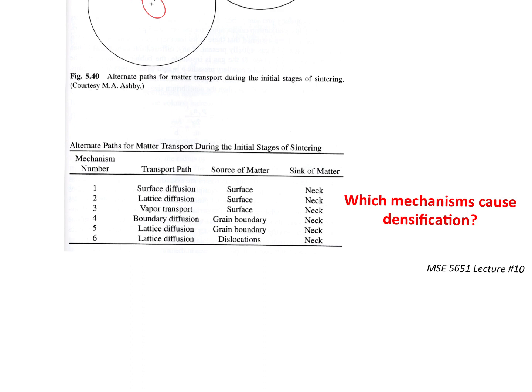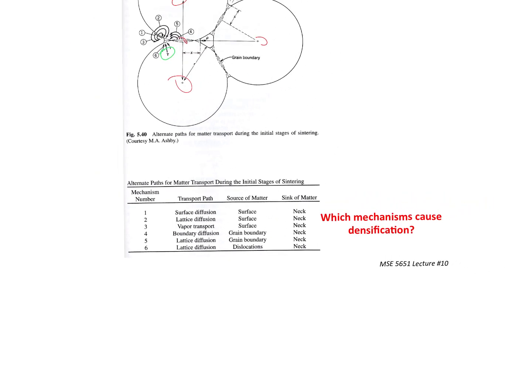You're taking it from the surface and you're transporting it to the neck, but you're not shrinking the space. So you're taking surface and putting it into the neck area. All you've done is you've made that surface smaller, but you haven't caused the spheres to come closer together. Does that make sense? And so on that note, we also have surface diffusion from the surface. So it moves along the edge here and ends up in the neck. It's happening all over the place. None of those are causing the centers of those spheres to come closer together.